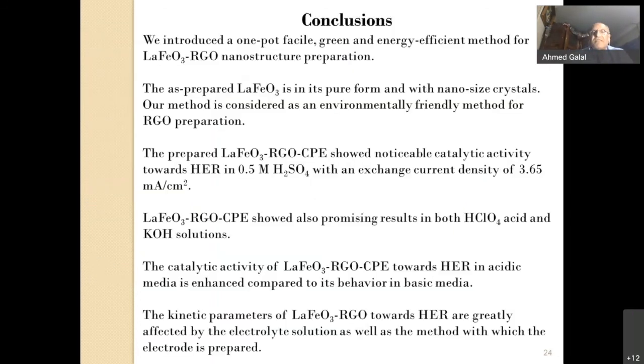electrochemical conversion process. In conclusion, we have introduced a one-pot, facile, green and energy efficient method for the preparation of a composite of a perovskite and a reduced graphene oxide. No need to use a high temperature for the calcination of the perovskite to obtain it in the pure form. And it was also a one direct transformation of the graphene oxide into reduced graphene oxide.